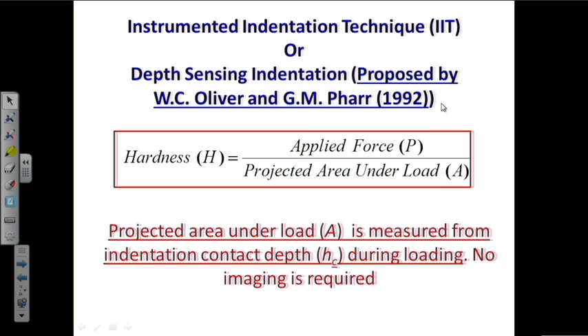According to this indentation technique, the hardness is defined as the applied force P over the projected area under load A. Remember, focus on the projected area, whereas the hardness defined in lecture 1 was based on the residual area under load. The projected area under load A is measured from the indentation contact depth HC during loading. Therefore no imaging is required in instrumented indentation, and that is the advantage of instrumented indentation, because we do not have to monitor the process of indentation, and we do not need to capture the images of each indentation after each indentation is done.